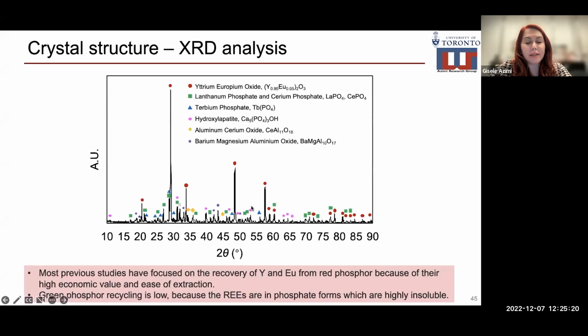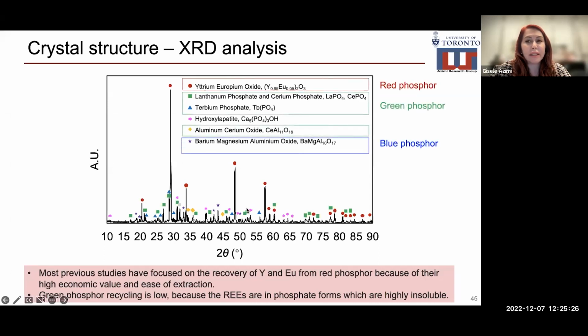We first conducted X-ray diffraction analysis to identify the crystal structure of the sample. We found that it contains red phosphor, green phosphor, and blue phosphor. Red phosphor is yttrium europium oxide. Green phosphor is phosphate of cerium, lanthanum, and terbium, and aluminum cerium oxide. And the blue phosphor is barium, magnesium, aluminum oxide. Most studies in the past focused on the recovery of yttrium and europium from the red phosphor because of their high economic value. But green phosphor was discarded because it contains phosphates that are not soluble in acid.